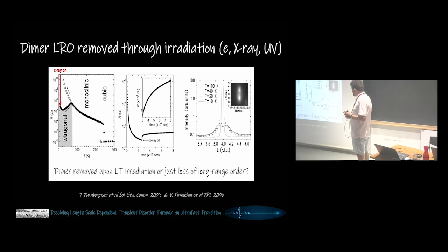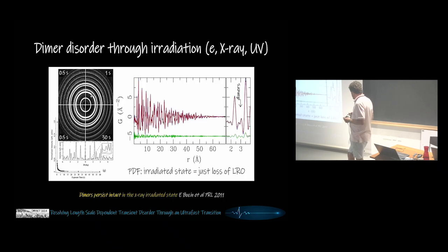Another interesting aspect of this system is that you can melt the long-range dimer order in the monoclinic structure by applying any kind of radiation: X-ray, ultraviolet, or electron beam. Then the system goes not to cubic, but to a tetragonal average symmetry. And you have these diffuse scattering wings that develop at low temperature. You can then reset by annealing the system. As it turns out, we applied PDF methodology there as well.